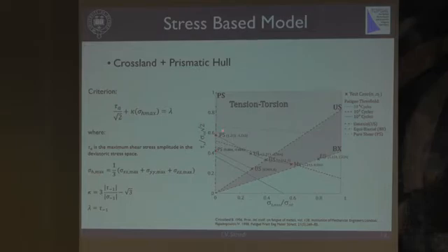And here we have, for instance, our range of experiments, and what we've done is we've plotted, on each of these radial lines, where they are compared to those lines. So if the criterion were correct, then what we would have is something more or less parallel to these lines, and you can see that for these kind of lines down here, this is quite reasonable.